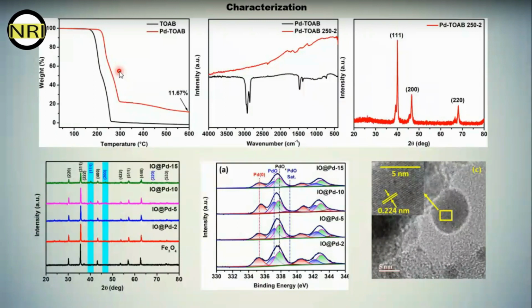So if I heat the palladium TOABr at 250 degrees C, I can get only palladium, and this organic part will be decomposed or removed. That's why I heated at 250 degrees C. To confirm whether it is fully decomposed or not, I took the IR of the palladium TOABr and the post-heated palladium TOABr. These are the signature peaks of TOABr at 2900 and 1500 centimeter inverse. After heating at 250 degrees C, we cannot see those peaks. That means they have disappeared, they are decomposed, so there is only palladium.